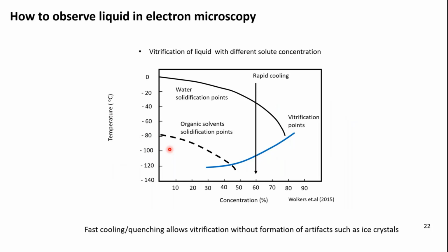To observe liquid electrolytes, we use a technique called vitrification. Vitrification is the process of freezing so rapidly that the liquid molecules do not have time to crystallize. So if you put just water molecules in the TEM column, they will end up evaporating. However, if you cool the electrolyte fast, it is vitrified and does not evaporate in the TEM column. When it comes to organic solvents, where solidification points are pretty low, the success of vitrification is pretty high, unlike water molecules. And considering we have high salt concentrations, vitrification points go up. So even if the speed is not so fast, you can still have high success rates of vitrification. And this way, we can preserve liquid electrolyte in a frozen form inside vacuum, and you can still see features with the presence of the liquid electrolyte in the TEM column.